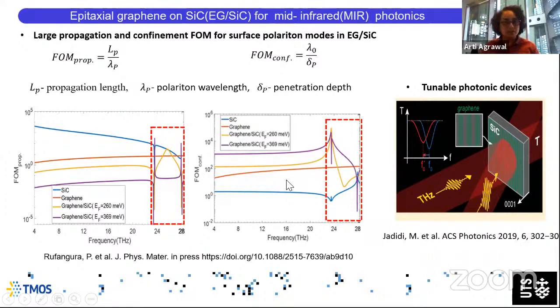But if you look at the second figure of merit, which is the confinement, that's the wavelength divided by the penetration depth into the material. And here is where things get really interesting. You can see from here that the confinement figure of merit improves tremendously if you have graphene on silicon carbide. So the purple curve here, you can see that you get really good confinement in the Reststrahlen band compared to say plain graphene or plain silicon carbide. So by combining these two materials, we can really confine the wavelength of light or the spot size, etc., that we would be able to get. So I'm going to talk a little bit more about this.